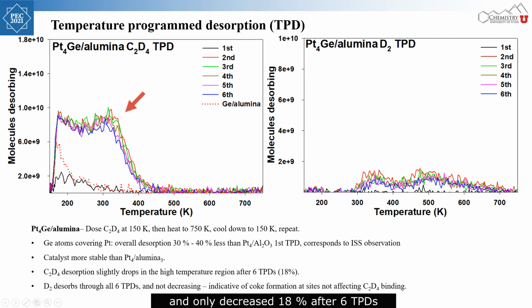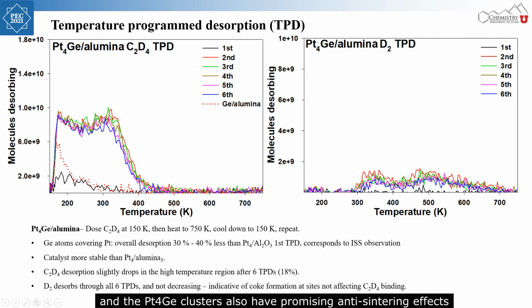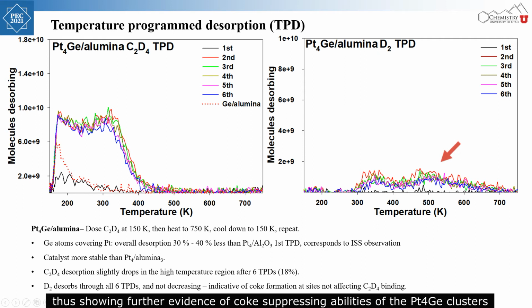the high temperature peaks are very similar in intensities and only decreased 18% after 6 TPDs. This indicates coking did not occur for platinum-germanium clusters, and the platinum-4 germanium clusters also have promising anti-sintering effects. Dehydrogenation was effectively suppressed in all TPDs, thus showing further evidence of coke-suppressing abilities of the platinum-4 germanium clusters.